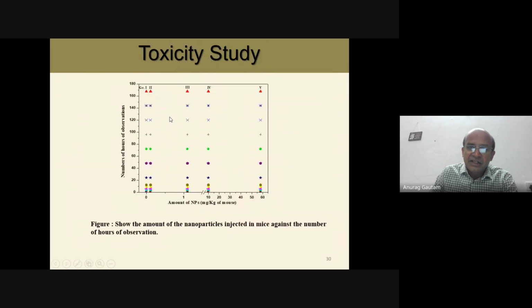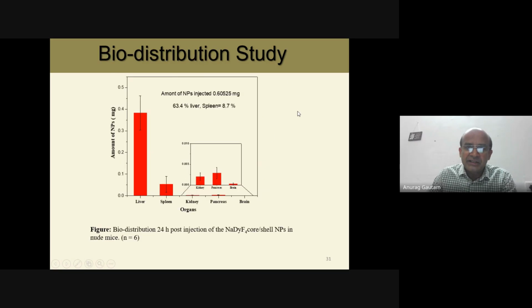And then we studied the toxicity with this nanoparticle also. We injected in the mouse model, in the mice, and we studied the basic toxicity issues with this nanoparticle, not with the blood sample or that. We injected the particle by tail vein injection, and all the organs were taken out. Their behavior was monitored during that period, and the organs were digested in aqua regia, and we studied how much is in each part. The mice behaved very normally. How much got injected is relative to the mouse weight in kg.